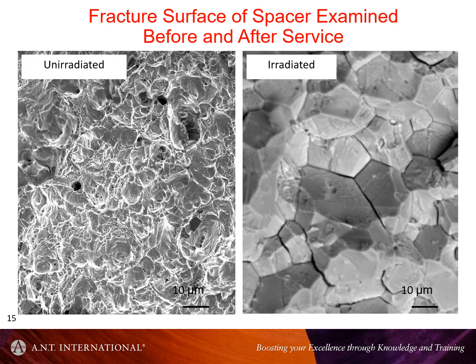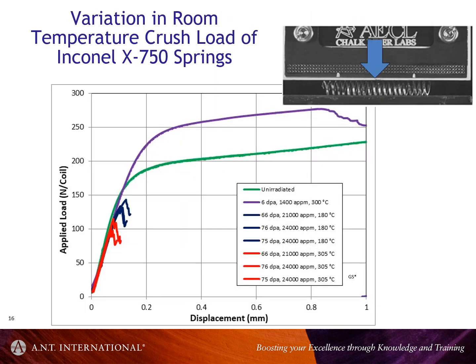So when the material failed, I mentioned they failed along grain boundaries. So you had this classic intergranular failure of these spacers irradiated for a long time, and they would be ductile if it was unirradiated. So one can summarize the properties of these springs from results of crush tests. Their function in the reactor is to hold up the fuel channel. So long as they can withstand the pressure from the fuel channel, that's okay, as long as they have enough load carrying capacity.